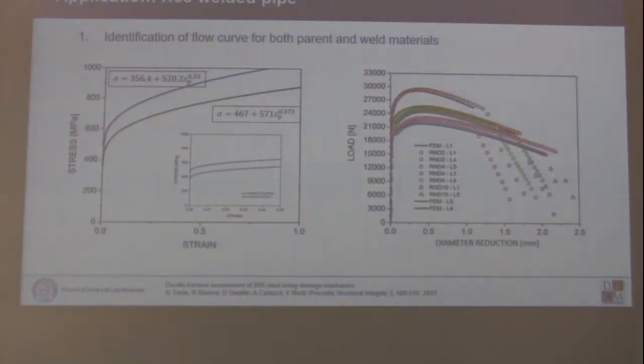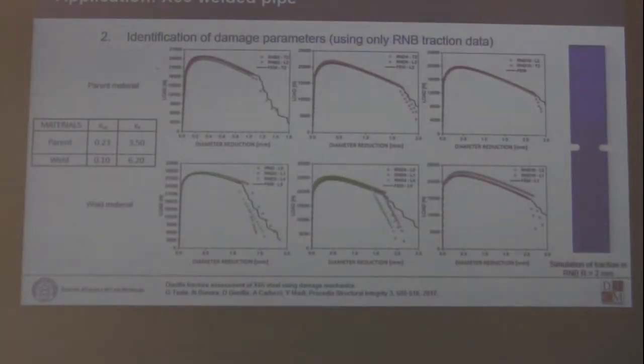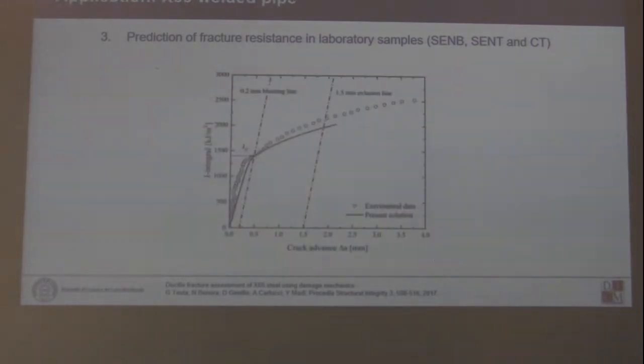I will quickly go to the final results. Okay, this is the validation for SENB, SENT, and CT. Again, when we identify the damage model, we don't change anything more. We don't have to go back and forth with new experiments to adjust the damage model parameters. This provides the basis for transferability. You can predict the crack resistance curve.